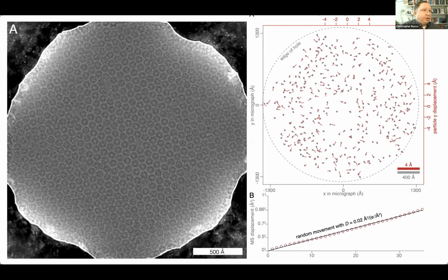And if you track the particle position of every single one of these particles within the hole during a typical image, so here's going all the way out to 30 electrons per angstrom squared, you see none of the particles move by more than an angstrom. And you can see they're also linear in mean squared displacement.